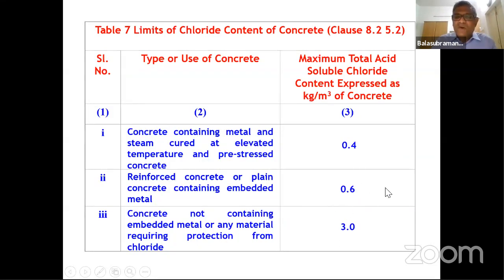But unfortunately, the code is giving 0.4 kg per meter cube for precast concrete. But the IS code says this 0.6 kg per meter cube should be at the time of placing the concrete. They are not telling what the threshold numbers should be after 10 years or 15 years or 20 years down the line. So this is only for the newly built structure.